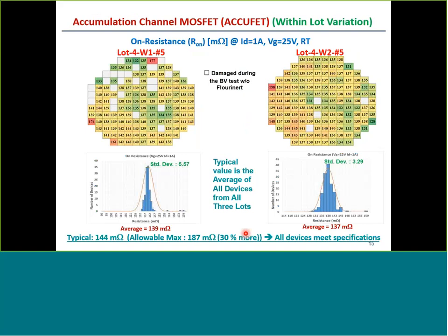So this chart shows the distribution of on resistance across 2 wafers. You can see a lot of blank spots. Unfortunately, when the testing was being done initially, there was some arcing experienced, and we lost a lot of devices because we were not using Fluorinert. Since then, we have remedied this, and we are now no longer experiencing a problem.